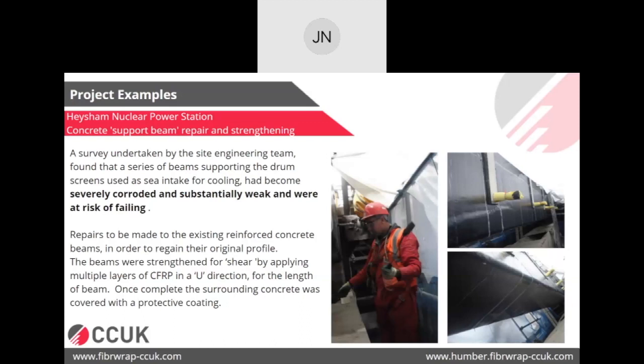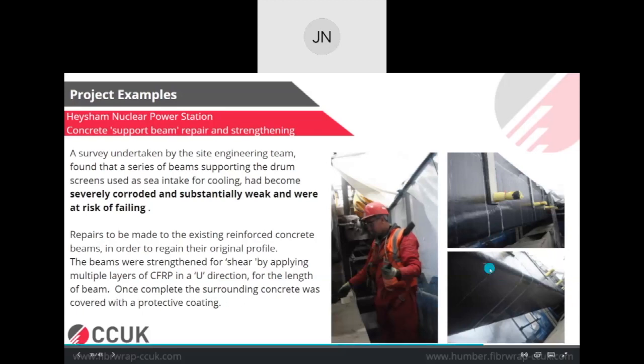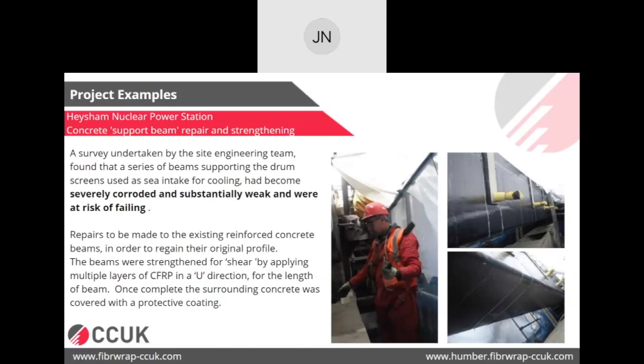So the concrete was getting eroded, and there was major spalling and corrosion in the reinforcement. So they needed to strengthen it because the equipment on top of these beams was quite important. So it was basically a nuclear facility, but the strengthening we've done was mainly for the waterfront structure. So we strengthened that using carbon fiber strengthening system purely because of the outage they could afford was very small, and they could not go with traditional method of strengthening of putting additional steel section on top of it. And that's why again FRP was used purely because of the time constraints they had.